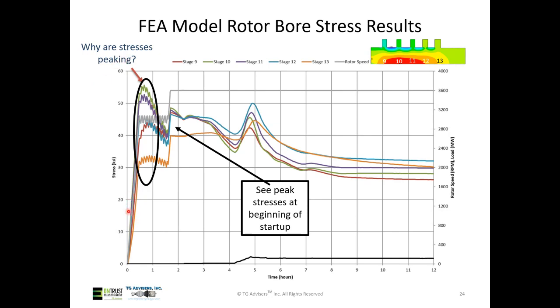So when you look at the criticality of the startup, we have to be very concerned about the ability of the rotor to withstand this part of the startup, particularly if it's an older rotor, because it's going to have those poor material properties because it hasn't gotten significant heating yet. Out here, although when we start loading, we see a higher stress peak again. We're not concerned, or not nearly as concerned, because now the rotor has a lot of temperature and it's got very good material properties.